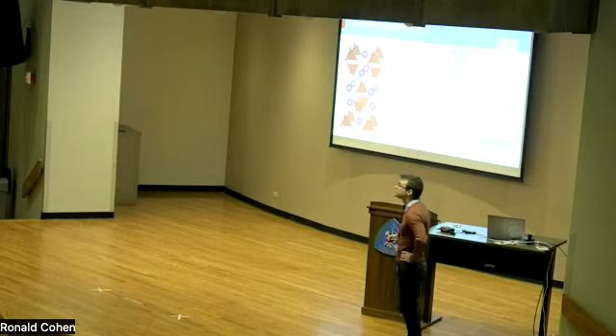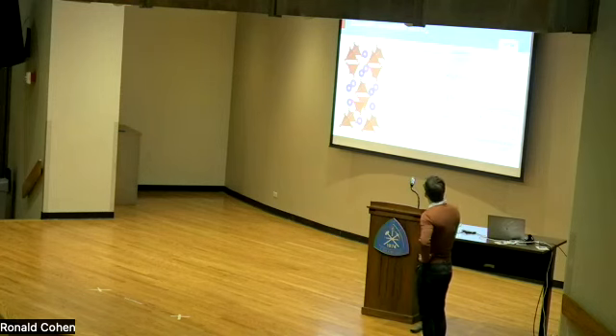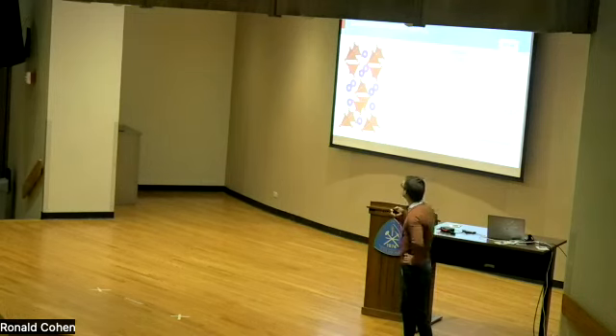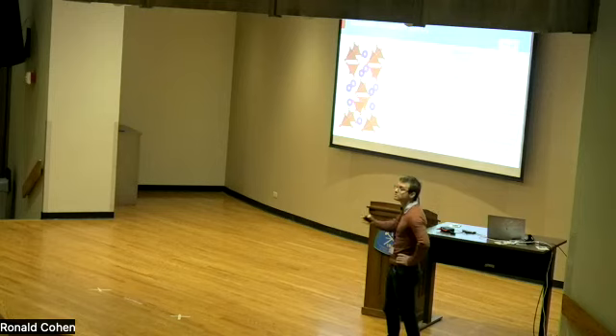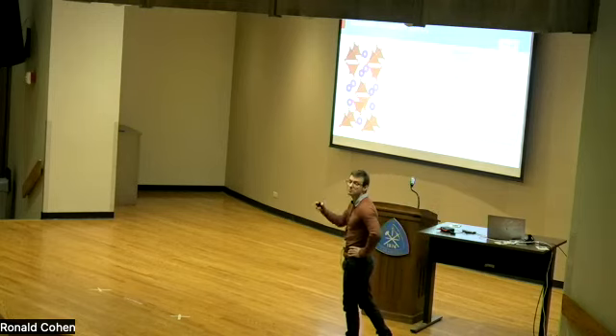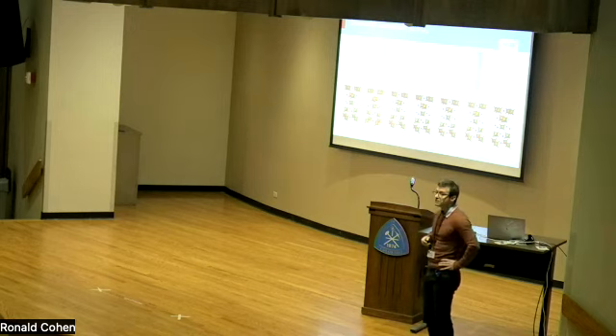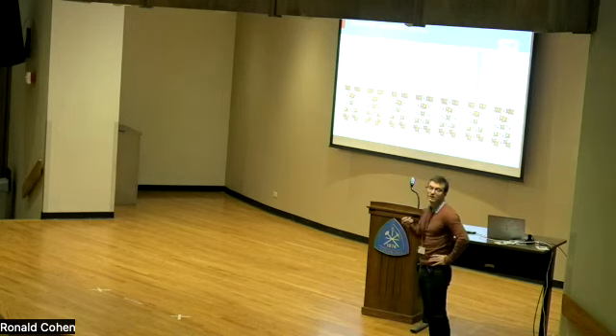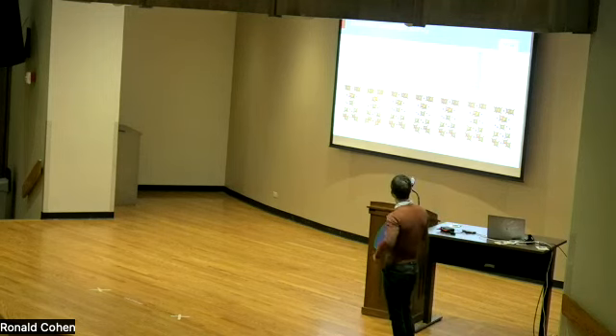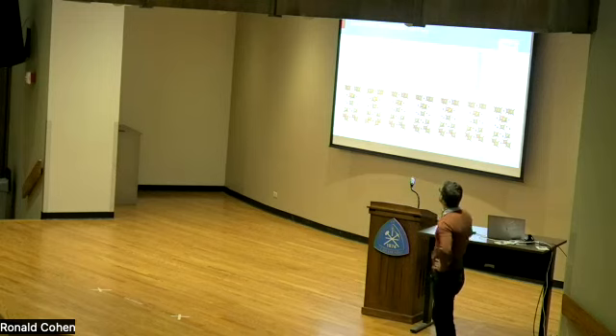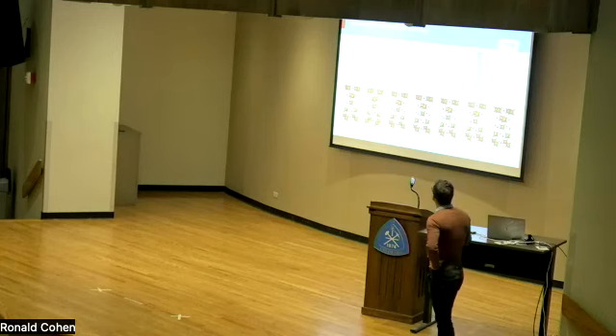Long story short here, because this is really a classical exercise that you can do to check how many polar modes you expect in the structure and how they should behave. Here, I'm just going to concentrate on this red square, where you can see that for those modes polarized along the z-axis, which is the one I'm interested in, there are 7 active modes in the low symmetry phase, and in the high symmetry phase, 3 of those modes become silent. So something very simple. This is what the infrared reflectivity spectra look like at 10 K. Again, long story short, everything works remarkably well. You find the 7 modes that you expect to see. And you can quite easily associate them to all the vibrational patterns based on calculations or even intuition, I would say.